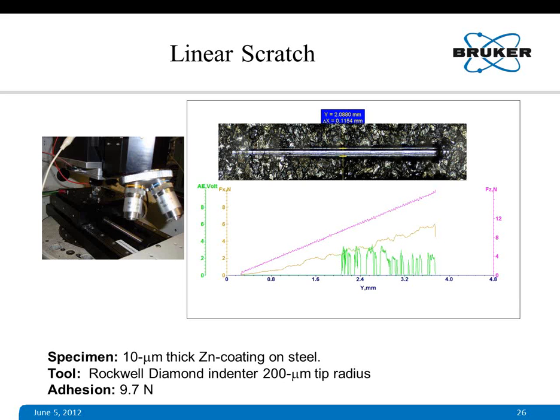Another linear scratch. This is on a very soft coating, like zinc coating on steel. Since both the substrate and coating are conducting, it's very difficult to evaluate the ECR signal here. It's easier to perform AE measurements on this. You can see the acoustic emission measurement shows when this stylus cuts through the coating and starts scratching the steel substrate. Lots of acoustic emission events are exhibited by this process, and we can pinpoint where it is failing. There is not much indication in the lateral force measurements.